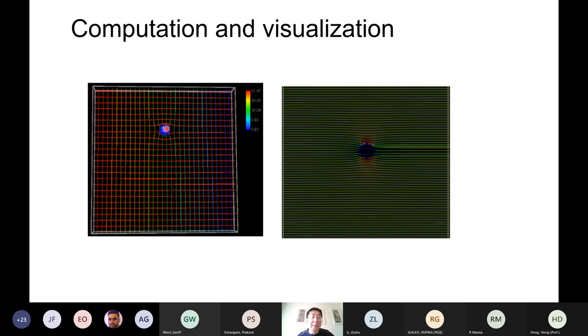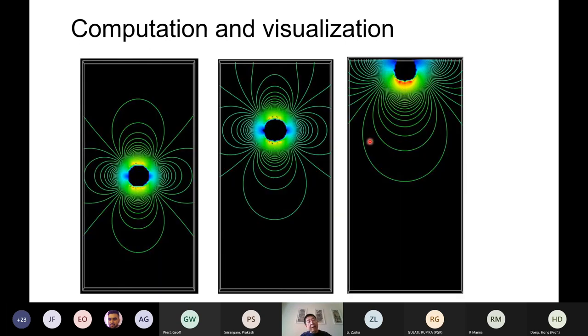You see around this part inclusions, the flow stream became different. If you look at here, this is the electric current density. Around these particles, the electric current density is much lower because they have lower electric conductivity, but not zero. If it were absolutely not conductive, the inside would not have any current. So you get a different current distribution, and from there we can calculate the free energy difference.